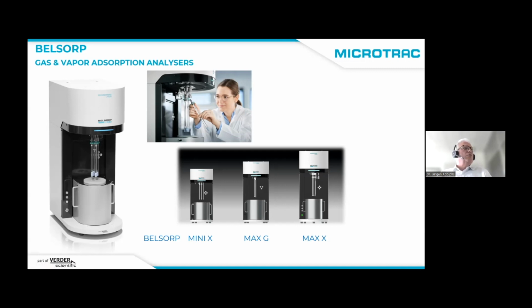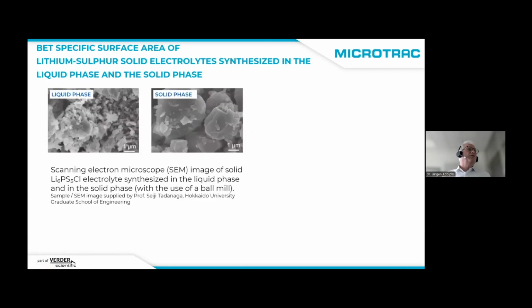So now I'm coming to an application, an example of a lithium sulfur solid electrolyte, which is synthesized in 2 ways. One is in the liquid phase and one was produced in the solid phase. And you see here 2 scanning electron microscope pictures of these 2 electrolytes. The problem is that these must be protected against air, in particular when we want to know pore size and surface area. Usually we handle our samples in air first and then do evacuation, but from the production, it needs to be protected already against air.